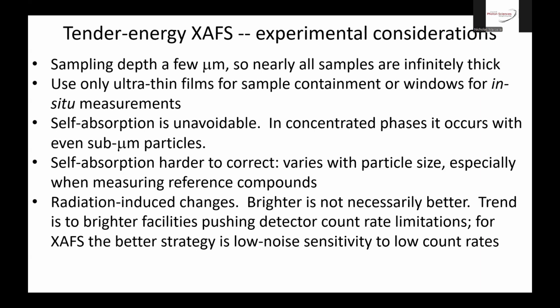And they did the same measurement on the same sample at an even higher power undulator beamline at the Swiss Light Source, and they saw only the second phase from the first scan on. And then they brought the sample to TESS, and we made that measurement with really low signal and really low detection limits. And we saw that, in fact, it originally started out as a third phase. And at APS, it was already at the second phase before they saw it transforming to another one. So you kind of have to be really careful for photon-induced changes to your samples. So just be aware of that.